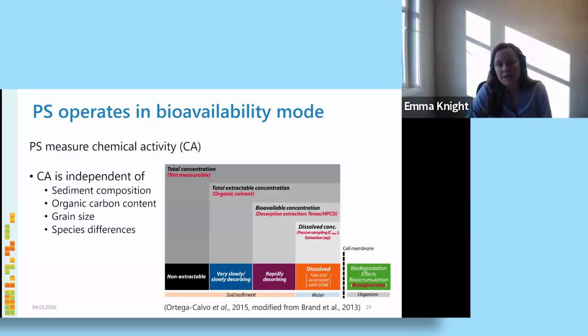And this is because passive sampling operates in effectively what I would call bioavailability mode. So when we look at this figure here from Ortega Calvo in 2015, where this was proposed as a way to help scientific compartments for a chemical in a matrix to be put into regulation or to be adopted by regulation, where the chemical activity is measured by passive sampling, for instance, which is in this dissolved concentration phase, so in the orange box, but also could be a little bit in the purple box. And it's directly related or directly in contact with organisms or plants or in this dissolved fraction. And this chemical activity is independent of sediment composition, organic carbon content, grain size, and species differences, meaning that passive sampling can be more comparable.